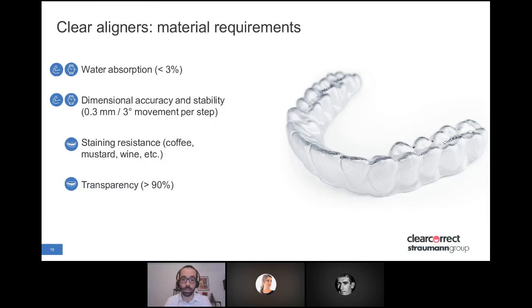Other requirements are that water absorption should be quite low, because the mouth is quite a moist environment. Dimensional accuracy and stability, because the movements they apply are really small. We're talking about 0.3 millimeters for translation and 3 degrees for rotations. So it should be accurate enough. And then, as already mentioned, staining resistance and high transparency.